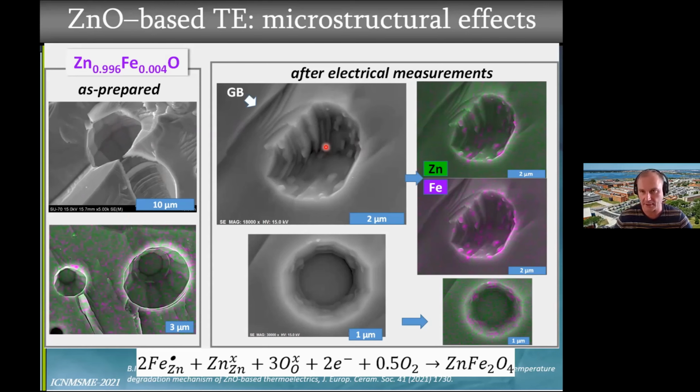Then what happens during the measurement is that oxygen exchange is facilitated in these pores, and here there are also fewer geometrical restrictions to the formation of new phases. This restriction could take place inside the dense bulk, of course, but here it is somewhat easier for these impurities to leave and to go out.